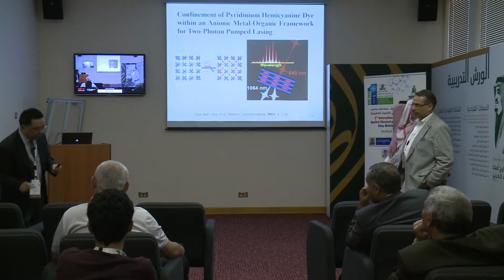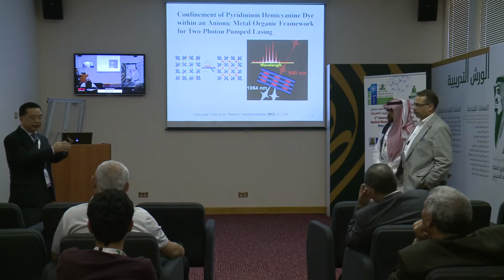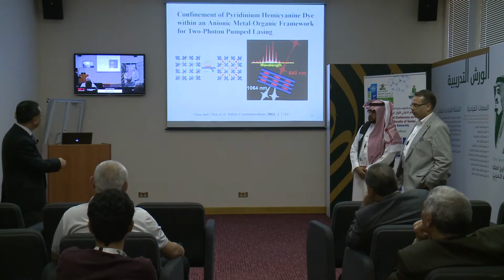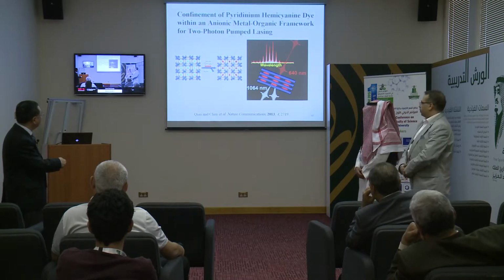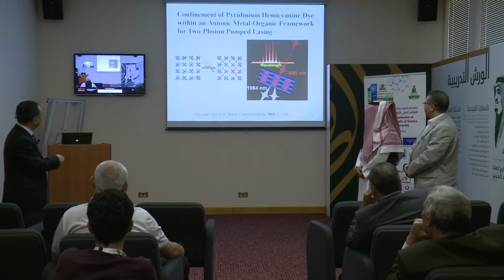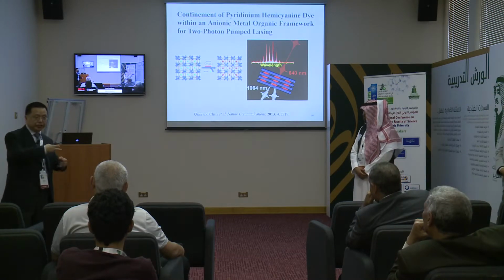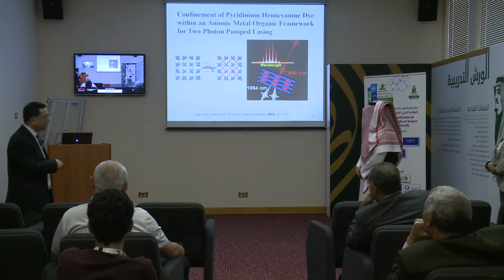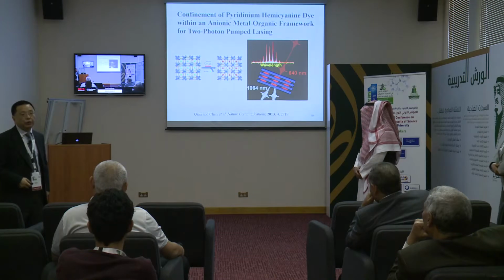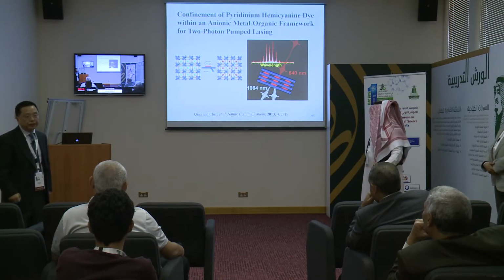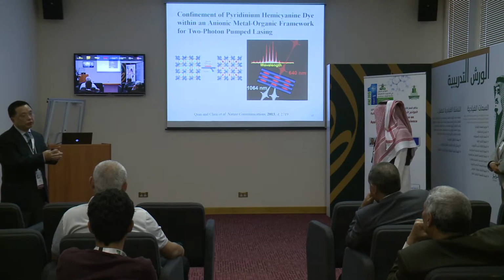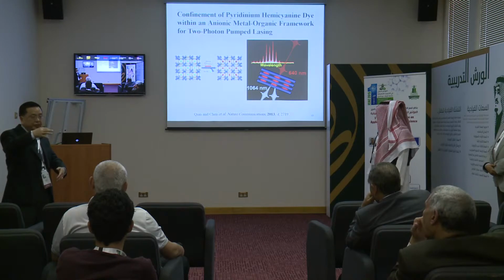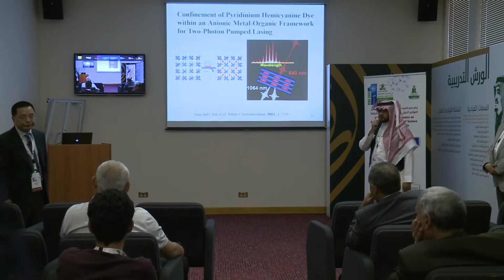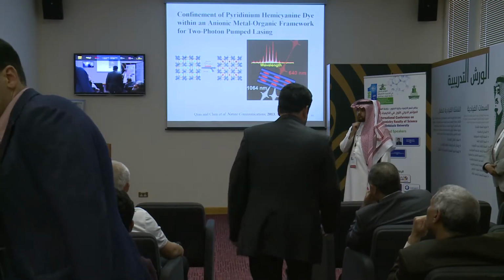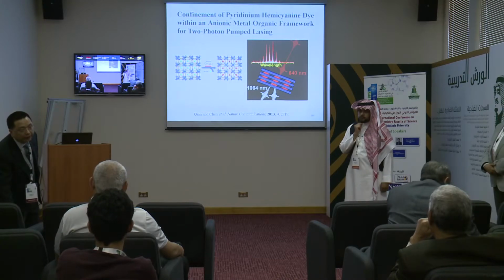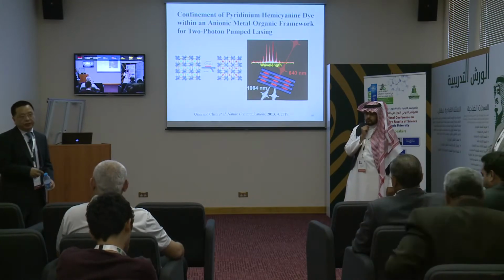The mechanism: in order to generate lasing, we need to have a suitable cavity. So the suitable cavity, I think, is quite good. The reason is because these dye molecules also have two-photon activities. So basically, long wavelengths can generate high energy, short wavelength lasing. So originally, this dye molecule has this property. So here, the pore basically tries to confine. So the luminescence property has been significantly enhanced. The quenching effect has been diminished. So the dye itself already has upconversion property. I think yes. And then you just encapsulate it, and it enhances it much more. Right, because it's oriented. Yeah, exactly.